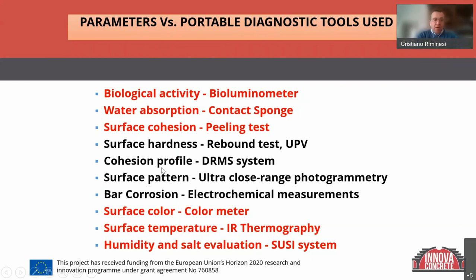damage on the surface. The pattern of the surface can be checked by ultra close range photogrammetry, and the bar corrosion by electrochemical measurement, the surface color by color meter, and the temperature and the humidity by IR thermography and by the SUSI system that we saw in the previous presentation, to check the humidity and the salt presence in the bulk of the material.